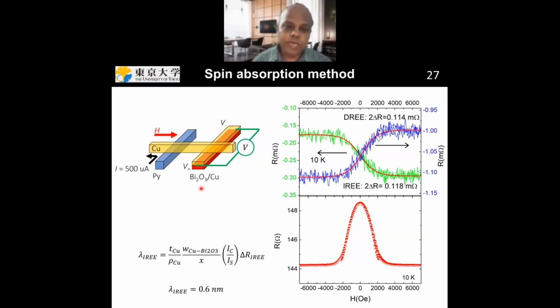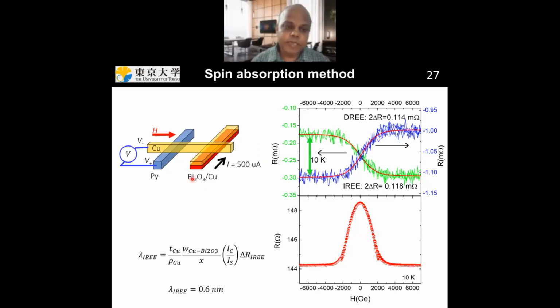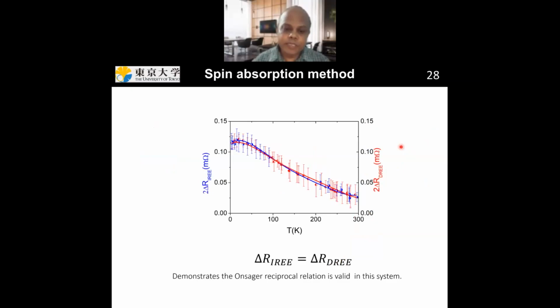In the same experiment, you can also do the direct Rashba-Edelstein effect. In this case, you pass current in this via here, create spin accumulation, and detect it non-locally, and you will get this green curve. You can clearly see that the magnitude of the signal due to the inverse Rashba-Edelstein effect is exactly the same as the signal due to the direct Rashba-Edelstein effect. We also measured these signals at different temperatures, from 10 Kelvin to room temperature, and found that the two signals have equal magnitude. This demonstrates directly and experimentally that Onsager's reciprocity is not violated; it is valid in this case also.